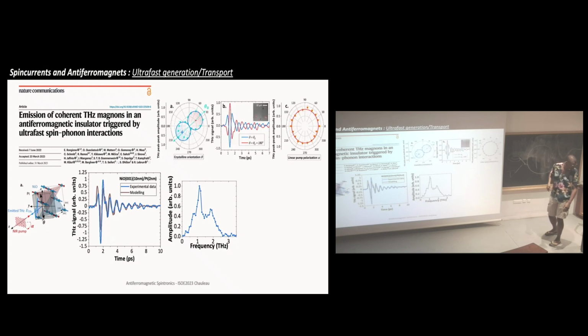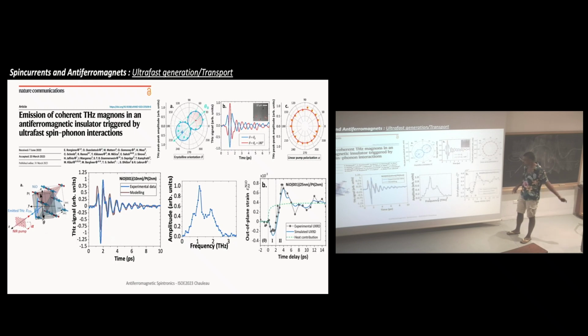And I will go a bit faster. So the nice thing here is that compared to the other study, they don't have any polarization dependence. So it's really related to something else, and they explain it the following way. They did some ultra-fast diffraction this time. So what's happening is that when you shine light on the platinum, it will start to expand, and by doing this, it will contract a bit the NiO, and the NiO is magnetoelastic. That means that if you change a bit this structure, if you put a strain on it, then by magnetostriction you will kick the magnetization a bit, and then you will trigger some dynamics. And then they follow the whole dynamics, and they can basically model what's happening here.